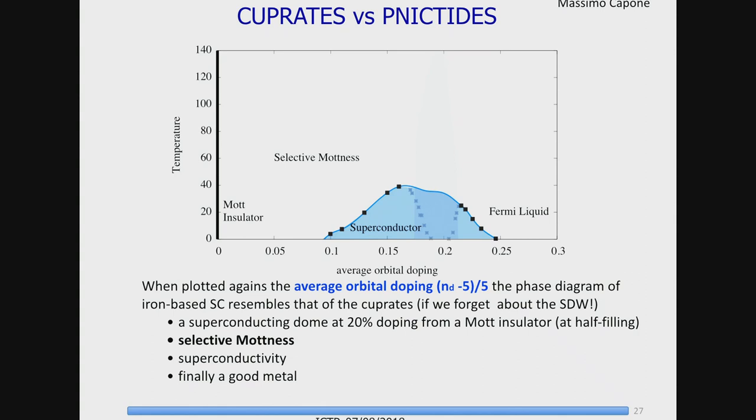Essentially, what is my story? If I look at my models, then at doping 0 in the iron-based, I would have the Mott insulator. Then I enter this selective Mott region, and then eventually I end up in the Fermi liquid. And superconductivity shows up right in the crossover region between the selective Mott physics and the Fermi liquid. If I go into the cuprate language, this is still the Mott insulator. The selective Mott region is the pseudo gap, which is a region where some regions of the Brillouin zone are gapped, they have the pseudo gap, and some others are not. And then you eventually end up in the Fermi liquid. So there is a clear correspondence between the phase diagrams, and superconductivity appears right in the same place, essentially,